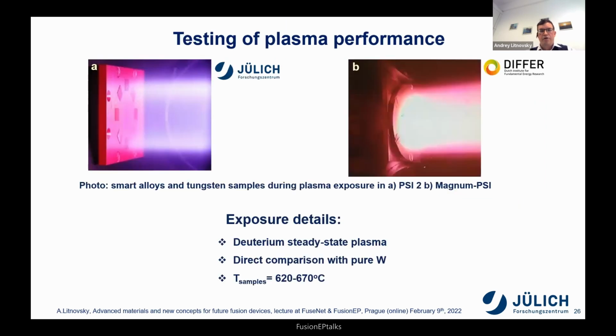Of course, since these are plasma-facing materials, a very important point is to see how good or how bad they are in the plasma. And for this, we made dozens of experiments in several facilities to see the effect. The materials were either simultaneously exposed with tungsten, or consecutive identical exposures were made, where the smart alloys and pure tungsten samples were subjected to deuterium steady-state plasma, at the temperature like in a power station first wall. And we had the chance to compare the results with a baseline material, pure tungsten.